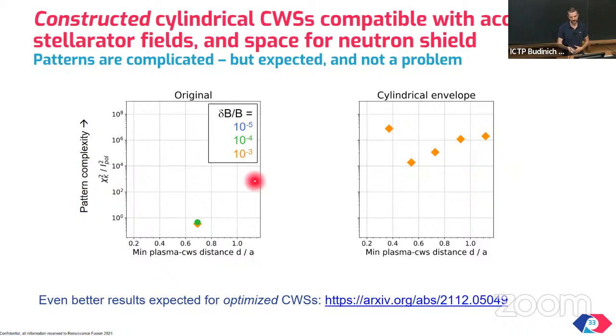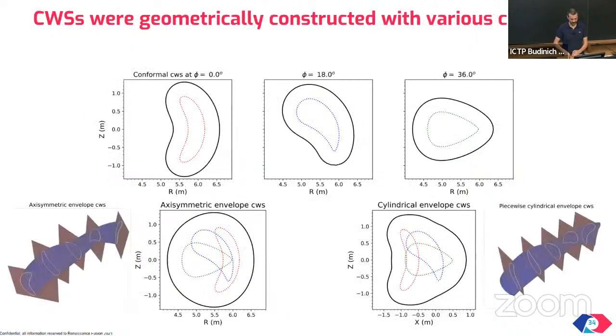These cylinders were geometrically constructed, but if you now start moving left or right or elongate or otherwise deform the cylinders, we expect to achieve even higher accuracies of the order of 1 part in 10^4. And in fact, we think that the best results will be obtained if we have a prism of non-circular cross-section, an extruded non-circular cylinder as shown in this picture on the right.